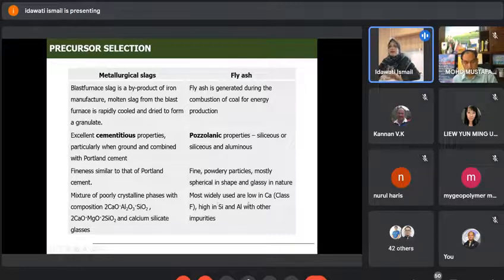Most widely used are low in calcium, which is class F. They are very high in silica and alumina, but they also come with other impurities. This is also something that we can talk about, the impurities. There have been papers about what zinc does there, how zinc affects. Those are others that maybe we can work together someday and discuss, what magnesium does there, but the contribution to the reaction is from the alumina and the silicate.